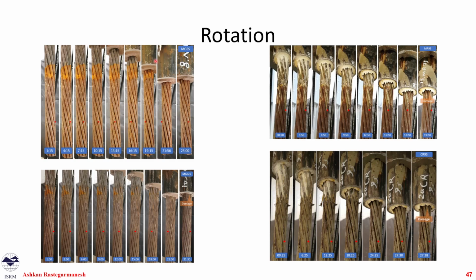Again, remember, these tests have zero rotation. So rotation was not allowed. But as we can see at the entry point, our cable is rotating. This is the last frame of the test. So at the end of the test, this point had, let's say, 180 degrees of rotation, went on the other side. Then when we release the load, this is the last frame after we release the load, we see that all this rotation went back to almost the same location, but not exactly the same location, which is very important. So we had a little bit of rotation stored in the test that was actually done during the test.